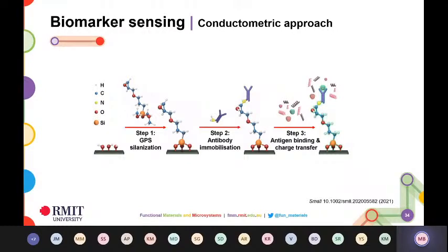So we thought, fine, let's go back to our oxides and see if they allow us to develop a biomarker sensor. A lot of the approaches which we take are usually conductometric. What we're looking for is a change in the electronic properties of the oxide, which we usually measure. So we went almost exactly with the same kind of approach. We started off with zinc oxide, which we silanized in this case to make it more hydrophilic. And then we attached the antibody on top of this. And essentially then the last step is you attach onto the antigen and you have a charge transfer happening as a result of the antigen binding onto the antibody, which you measure off as a change in the conductometric properties of the oxide.